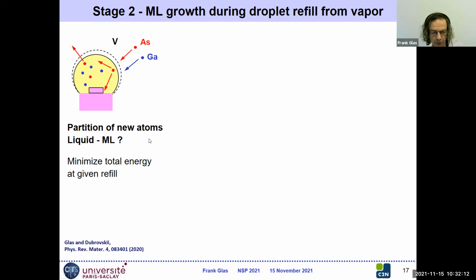So the big question is, what is the partition of the new atoms between liquid and monolayer? And as I said, I will find the solution to this problem by minimizing the total energy of the system at a given refill. So I will imagine that I have put a certain number of extra atoms in the liquid, and I will calculate the energy of the system as a function of the fraction which stays in the liquid and the fraction which goes to enlarge the monolayer. And the lowest energy for me will be the state that the system adopts.